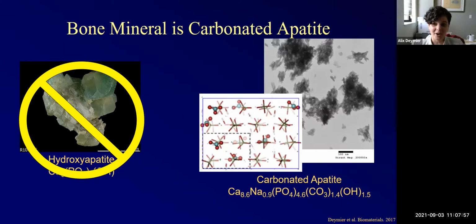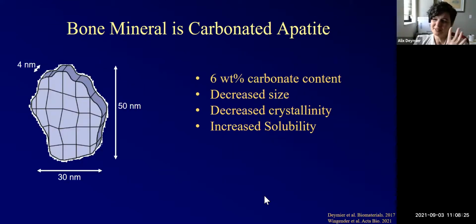But instead of just being calcium phosphate and OH groups, we now have the substitution of additional carbonates, and we have the substitution of sodium. Now, maybe you're dinging right here and you're like, carbonate. We already learned that bicarbonate is really useful for neutralizing acid. So this must be important, and you would be correct. But the carbonate has tons of other effects on the mineral. So if we think about bone, it has about 6 weight % carbonate. So not a ton, but pretty significant.